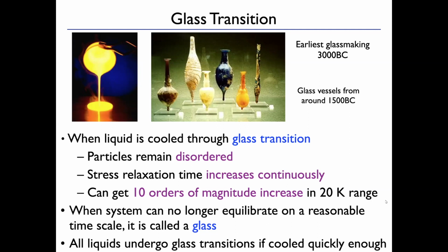Not only continuously, it increases dramatically. So for many, many glasses, you can actually get a 10 orders of magnitude increase in just tens of Kelvin. So the relaxation time is just shooting up incredibly rapidly. Once it shoots up that rapidly, it becomes very hard to equilibrate it. And so when a system doesn't equilibrate on a reasonable timescale for waiting, that's what we call a glass. And this is a generic feature. As long as you can avoid crystallization, you will always see this behavior in every system. And the interesting thing, if you looked at a snapshot of the glass and compared to a snapshot of liquid, you would not be able to tell which is which.